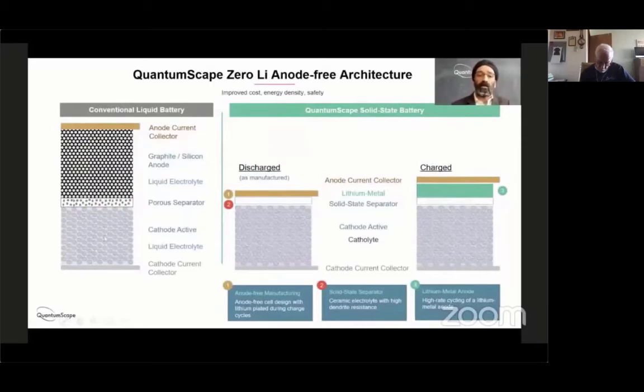And all the battery does is, when you charge it up, lithium ions are forced to move from the cathode through the electrolyte into the anode. When you discharge it, the ions move back down, and you can extract work back out of the battery. And if you had a solid-state separator, you could replace this porous polymer separator, as shown in the left schematic, with the ceramic separator, as shown in the middle schematic here, and completely do away with this graphite, carbon, or silicon anode. And you are left essentially with a 2-layer battery, which only has a cathode and a separator as manufactured. The anode is formed in situ on the first charge.